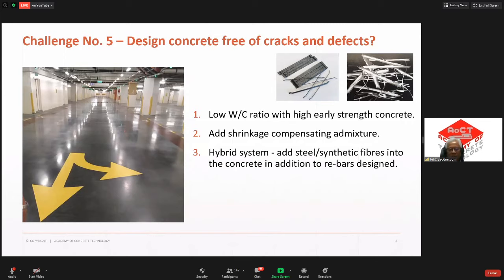And you know very well that when you add steel bar into the concrete slab, it's basically to control the cracks, besides taking the load, but the main purpose is controlling the cracks. But it's very difficult to position the rebars where they should be. In other words, sometimes the concrete cover is too much. For example, you should have a 50 mm concrete cover, but due to shoddy workmanship, the cover could sometimes be even 100 mm. So that's where you get a thick mass of concrete, and when the concrete shrinks, that's where it starts to crack. So these are the reasons why you'll find it very difficult to control cracks, all right?